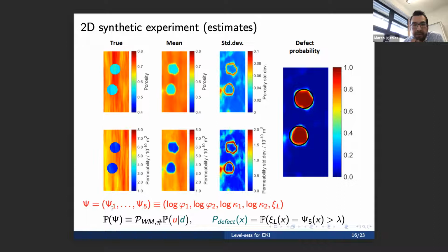Now, if you remember, we're inferring these parameters in this parameterization, but when we go one level up to the Whittle-Matérn one and compute the random fields that we later use from the truncated formula for the porosity and permeability, there is one that corresponds to the levels. So for the level set, which is what tells me whether I'm in the defective area or the non-defective area, because I have an ensemble for that, a distribution, a marginal for that, I can compute the probability that at a given point it's above the threshold, because above the threshold tells me that I'm in the defective area.